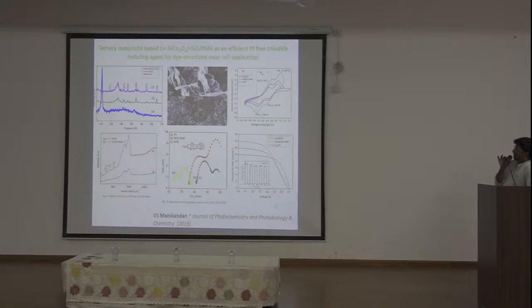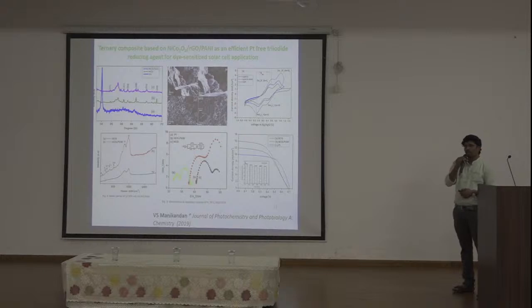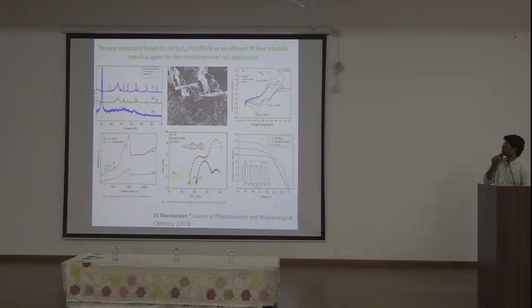The RGO is providing more active sites for the iodide and triiodide couple to participate, increasing the number of electrolyte molecules being reduced. So that's why higher dye regeneration happens, and the current density is increasing. So overall, the nickel cobalt RGO composite with in situ polymerization is increasing the overall maximum power conversion efficiency to 4.2.